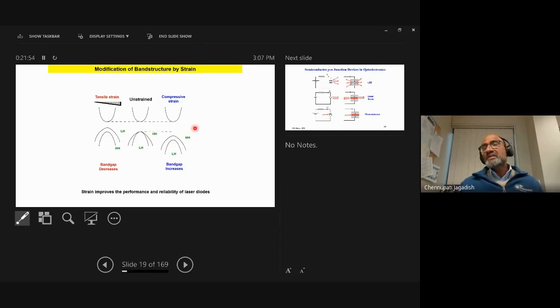So now you can see that instead of only alloying the semiconductors to tune the band gap, strain can also be exploited to tune the band gap. And if it is a tensile strained material, again, it reduces the band gap. And you see the light hole is on top now, whereas here the heavy hole is on top, and that changes the polarization properties of light emission from the lasers. You can make compressively strained lasers or tensile strained lasers as long as you stay below the critical thickness.